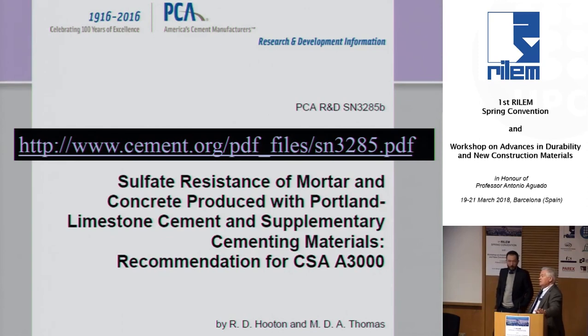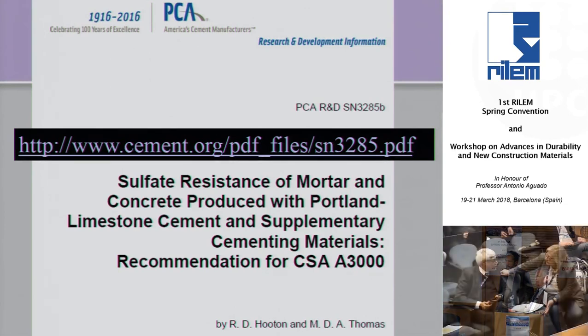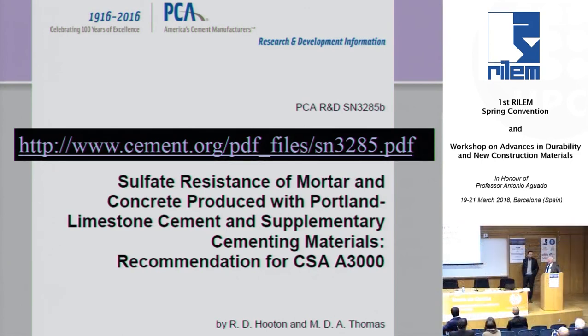And so they were nervous about bringing a new cement system in. And so we said, look, let's take a belt and suspenders approach. We put in a test, which we thought was a performance test. We put in prescriptive limits so nobody could get around it, saying you have to use a sufficient amount of fly ash or slag to mitigate the problem as well. But then we found out that the regular test method would give us that same performance. So we didn't see the need to have that additional prescriptive requirement in the system. It's sort of self-regulating. If you have the data to show that it doesn't expand in the mortar bar test, then you have sufficient mitigation.